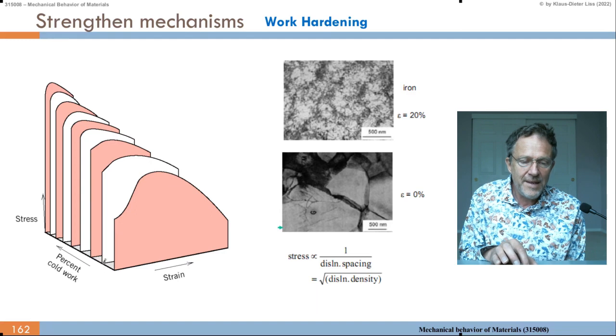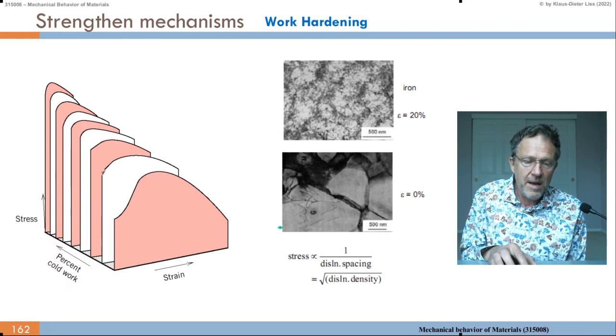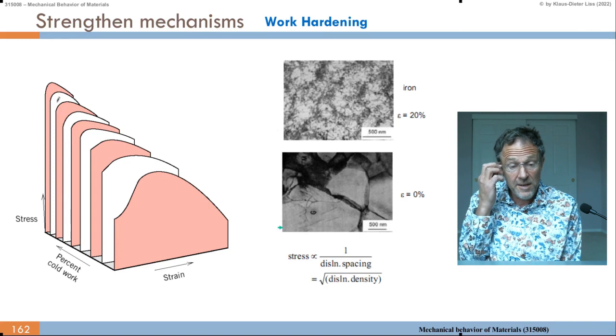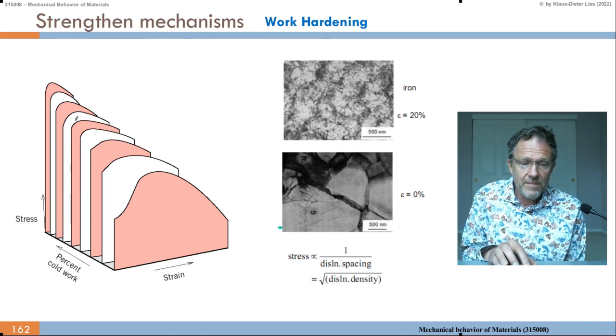Then in the second step, when it's already cold worked before, like rolling or drawing, if I have a little work hardening, then I get a higher yield strength here and eventually go through the UTS and necking it down. And so on. So with more and more work hardening, I get higher initial yield stresses. But then the distance to the UTS is not that high anymore, because this is initial percent cold work, but when I pull here, this is also kind of cold working. So the plateaus may go up a little higher, depending how I cold work it, but not so dramatic anymore.